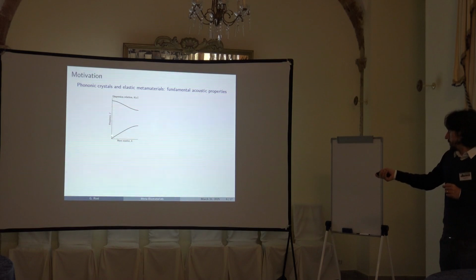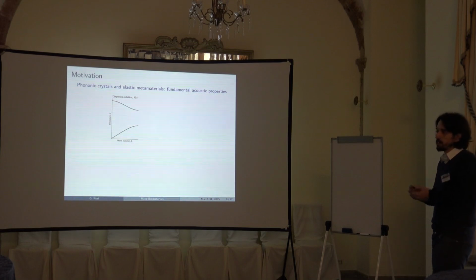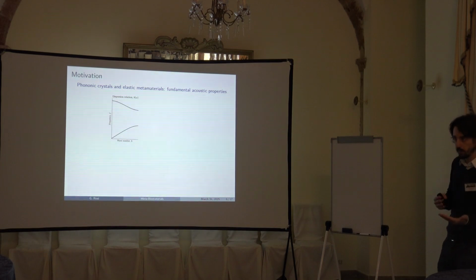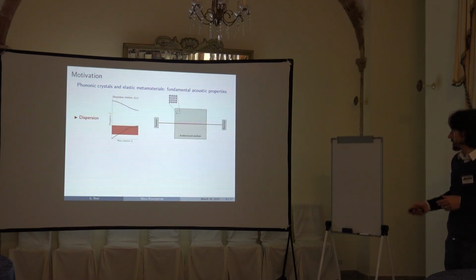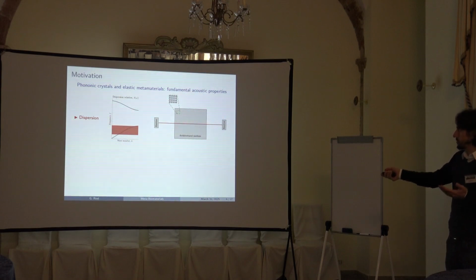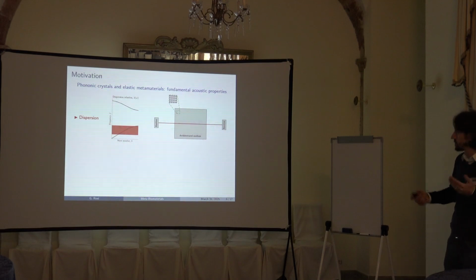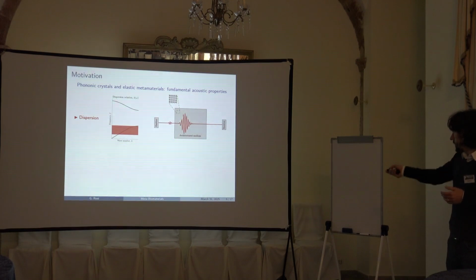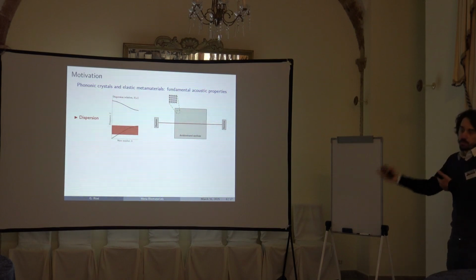This point here corresponds to low frequency and very large wavelength, and you can see that there is almost a straight line at the beginning, and this is the behavior you have when you propagate in a homogeneous material, a linear relationship between phase velocity and wave number. So what happens if you use a classic transducer, which is centered on a central frequency but has a bandwidth, and you send a wave in this range here? You see, this is not a straight line anymore, so the wave packets, depending on the frequency, will travel at different phase velocities and group velocities, and so the packet will distort as it enters the metamaterial and goes out the other side. This will be the experimental setup that we will use later in the experiments.